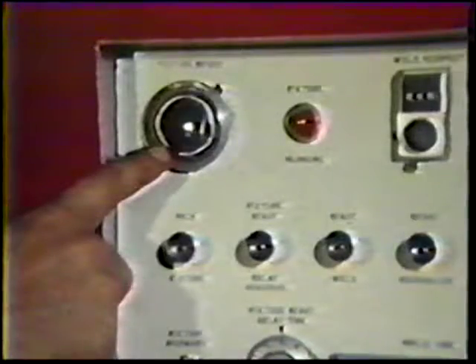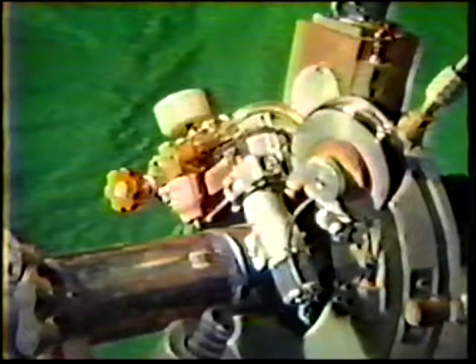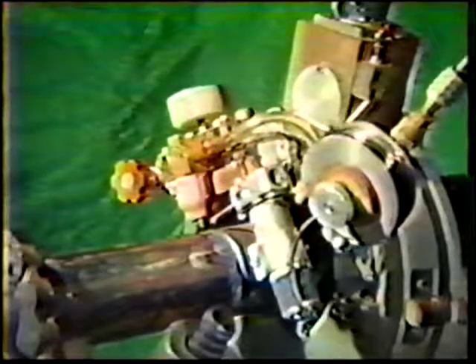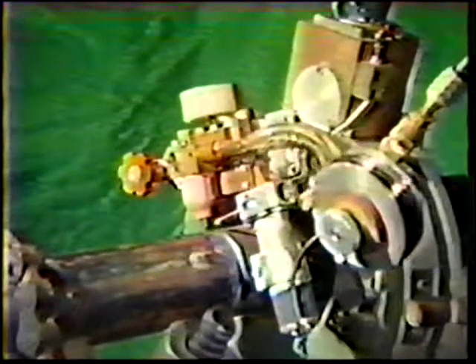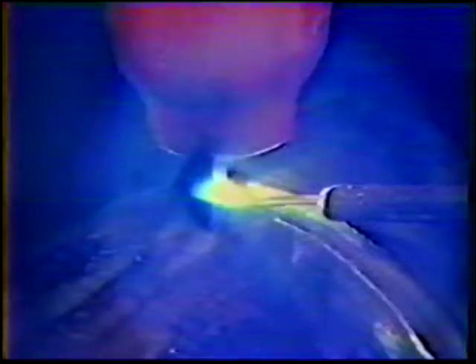The motor speed control controls the movement of the torch head around the sections of the pipe being joined. The speed of the torch depends on the size of the pipe or tube sections and the welding procedure variables. The rotation of the welding head is usually delayed at the beginning of the weld cycle until the formation of the puddle. The welding head travel can be set to run continuously around the joint in a smooth manner, or when using pulsed current, the head may be allowed to move in short increments during the high or low pulse.